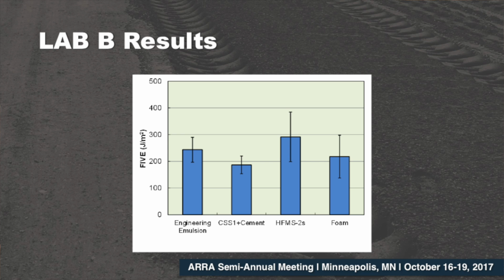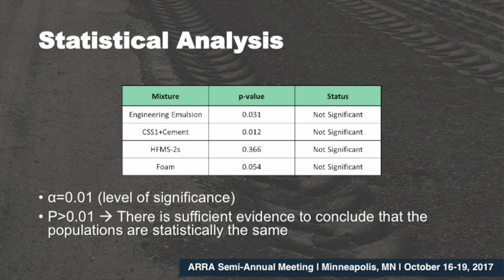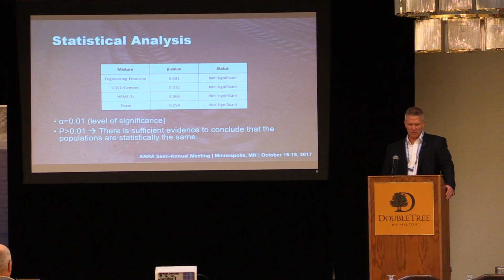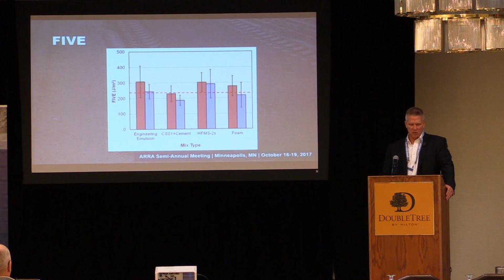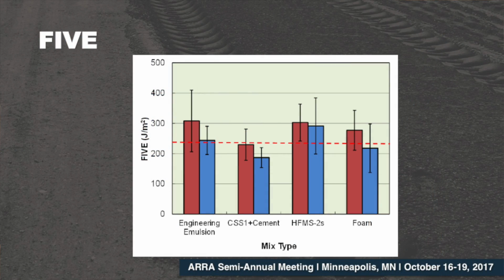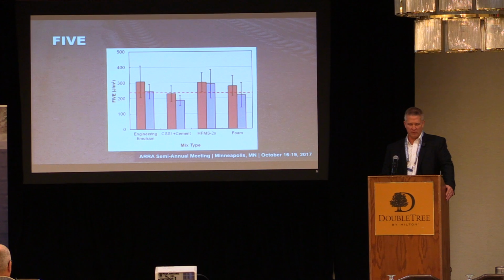And looking at the results and coming up with a statistical analysis on them, Dr. Sabori looked at that in depth and found that there was not a significant difference in the statistical value, looking at the p-value in his statistical analysis of the populations. So putting all that information together and looking at developing a performance specification and looking at developing some type of criteria for the SCB test for the fracture energy value, coming up somewhere between that 200 and 250 value seemed to make sense.